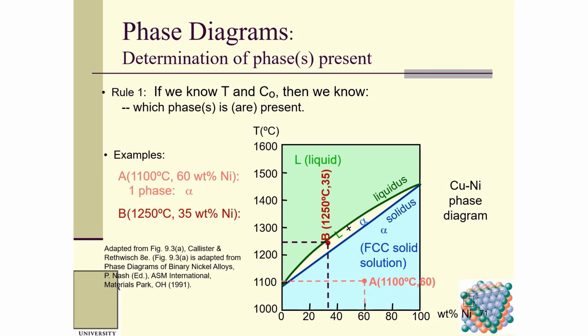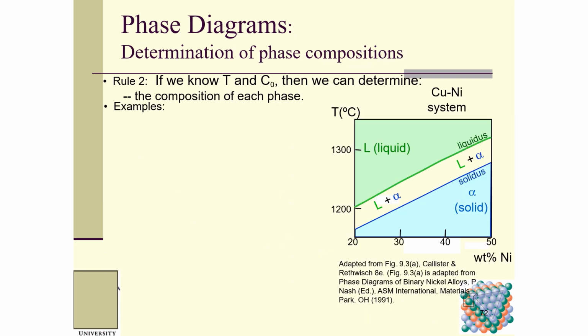Point B: 1250 degrees C and 35 weight percent nickel, and we know this is in the liquid plus solid region. Rule 2: if we know the temperature and the composition, then we can determine the composition of each phase, right? The composition of each phase.